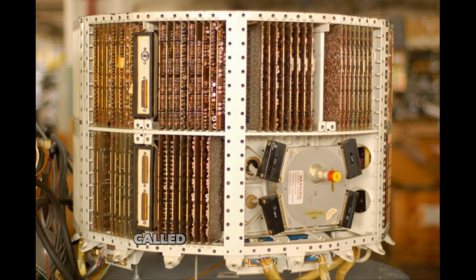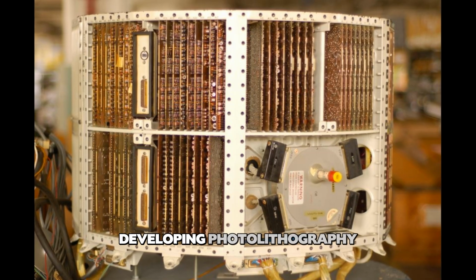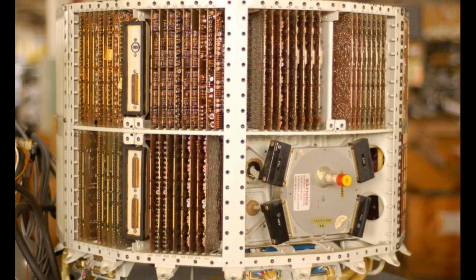He developed what he called the planar process. Instead of etching away material to expose junctions, he would grow a silicon dioxide layer across the entire wafer surface, then selectively remove oxide only where he needed to make electrical contact. The oxide would remain in place over the actual transistor junctions, sealing them permanently against contamination. He could diffuse impurities through windows opened in the oxide, creating transistor structures that were protected from the moment they were formed. The technique required developing photolithography methods borrowed from the printing industry.